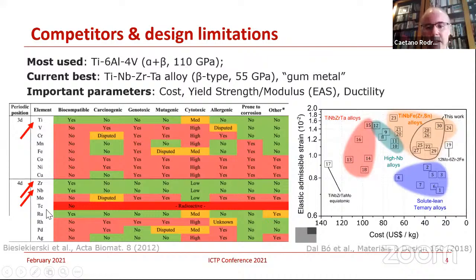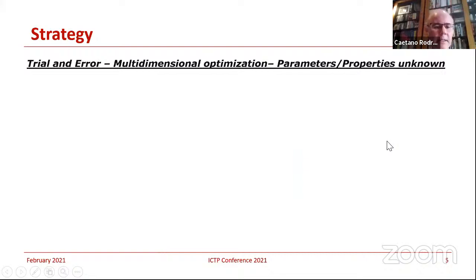Now, in this way, you are looking for alloys with this combination of titanium, niobium, and zirconium, and you hope that the elastic properties can reach this region, particularly at low cost. But the problem is what the composition would be. To do that, one strategy that people use a lot is materials discovery. Now, it's still very much trial and error. The problem is that you have a multi-dimensional optimization problem: you have to look for the best composition for a given system.